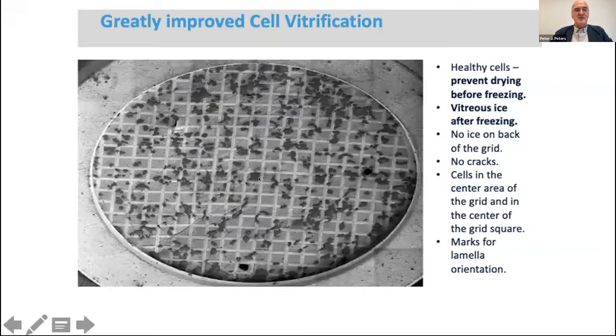And here you can see the result on a gold foil of mammalian cells growing on these gold foil grids. And we have really significantly improved this procedure by all the elements that you can see. I will not go into the detail, it takes me too much, but we have no cracks, we have beautiful vitrification. It is much easier to make lamellae of these vitrified cells because they are amorphous. If they have crystalline ice, it takes longer time.